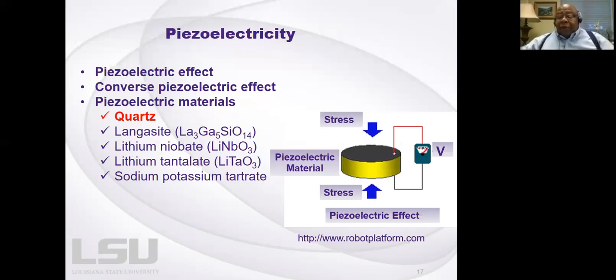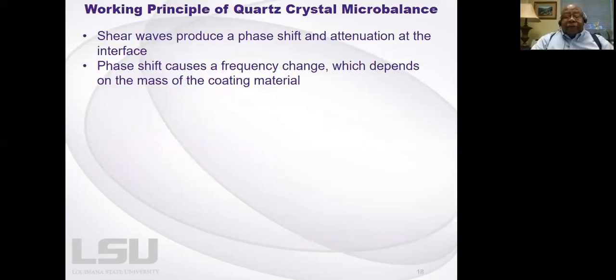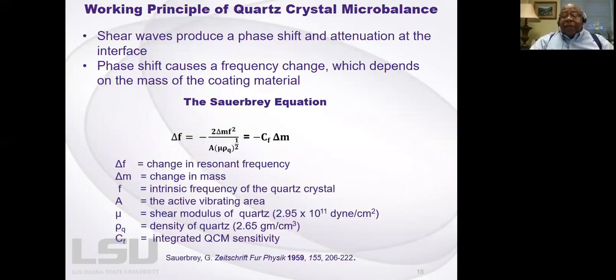And so many years ago, a scientist by the name of Sauerbrey figured this out. What he found was that shear waves produce a phase shift and attenuation at the interface when you add these materials. This phase shift causes a frequency change, which depends on the mass of material that you added to the surface. And so he came up with this equation that delta F is equal to minus a constant CF, and you can see the terms here that CF depends upon, times the change in mass.